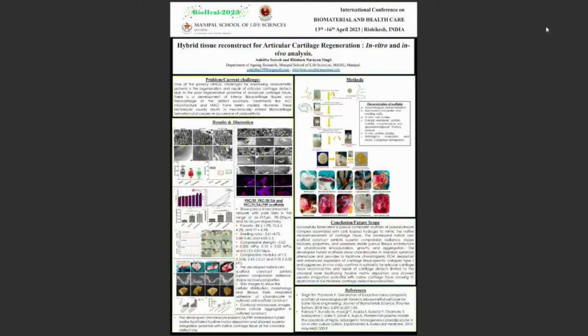And there are 3 types of scaffolds which we have compared. One is silk, chitosan and chondroitin sulfate. The other one is where we have put sodium alginate. And the third scaffold is where we have put sodium alginate as well as PRP, that is platelet-rich plasma. So what we found out is there is varying pore size in all the 3 scaffolds, which ranges from 60 to 300